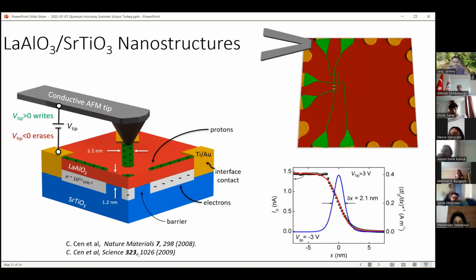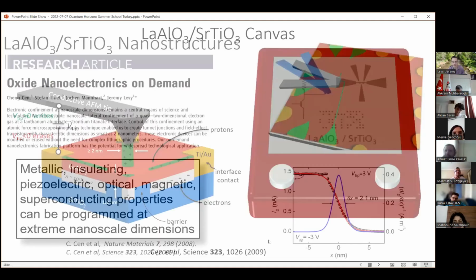So what we demonstrated back in 2009 is that if you write a line and you measure its conductance, and then you move across the line and try to erase it, and you measure the conductance as a function of position, it switches from being a conductor to an insulator when the tip moves only 2 nanometers. And so that gives us a measure of the width of these nanowires. So they can be as small as 2 nanometers, which is only 5 unit cells of the underlying lattice constant of the material. So this is extreme nanoscale control of the metal insulator transition.